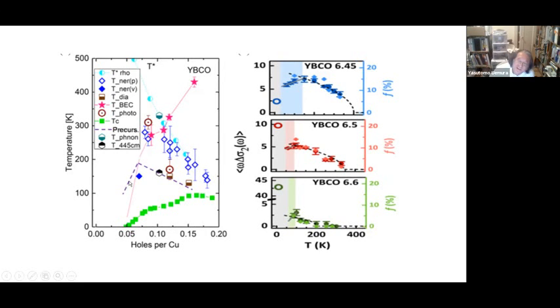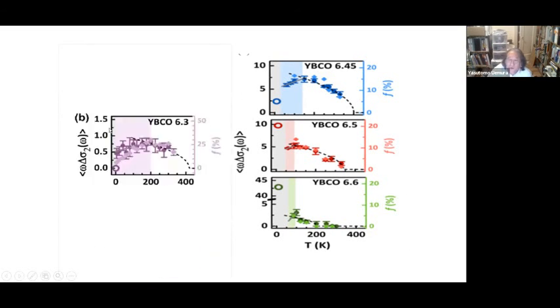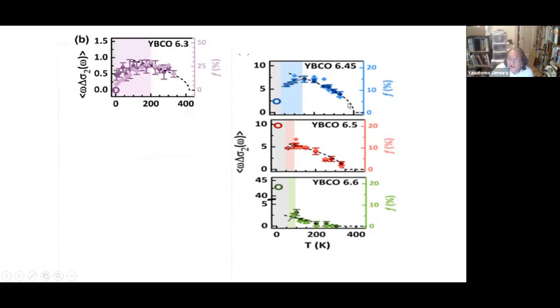If you like, this is still close to the following, this hypothetical Bose-Einstein condensation line or local phase coherence line, but it could be following this pair formation line T star. And then you can go to this lower concentration, more underdoped YBCO. Okay, so the onset temperature is rather high, but the superfluid density is very, very small.